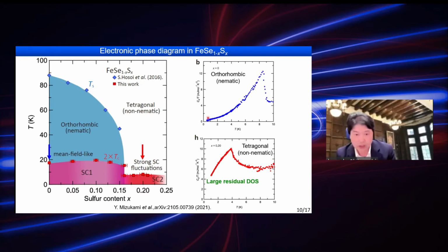Importantly, if you extrapolate this data to T equals 0, we have essentially no residual C over T within the nematic phase. However, outside the nematic phase, in the tetragonal phase, we see a very large residual density of states in the specific heat data. In the T equals 0 limit, we have a significant residual C over T.